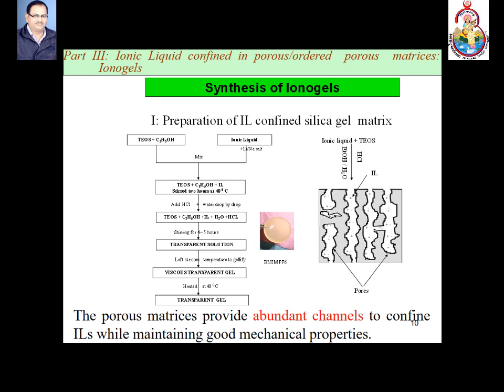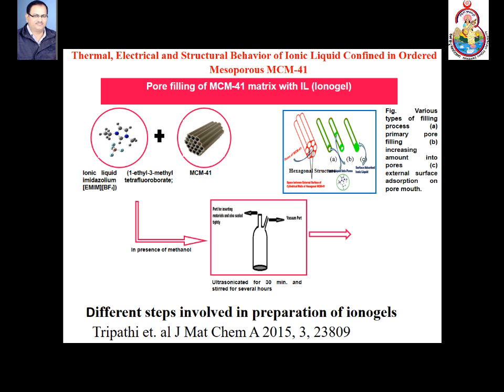Another class of ionogels, which are obtained by entrapping ionic liquid or ionic liquid salt solution in porous matrices, is synthesized. In such systems, the ionic liquid or ionic liquid salt solution, besides going into the pores, also goes into the interparticle spaces, and there are abundant channels for conduction, and therefore its conductivity is liquid like. At the same time, mechanical support is also offered. Some of the results on MCM41 matrix based ionogels in which a physical imbibition process was used, and the resulting ionogel electrolytes had very high ionic conductivity.